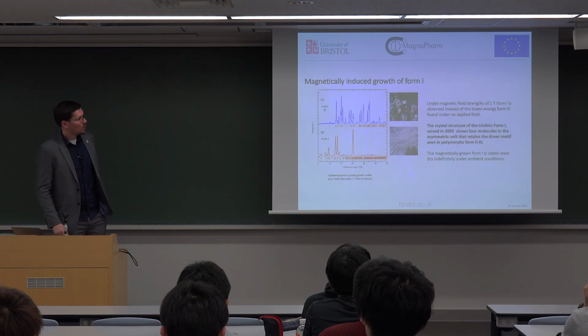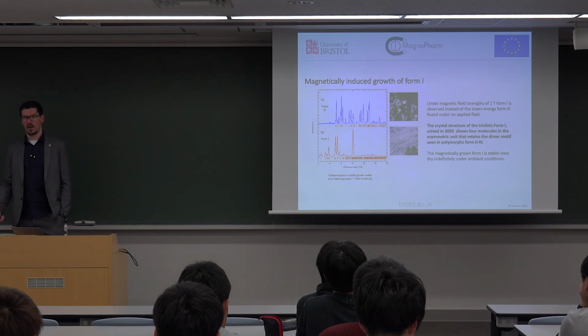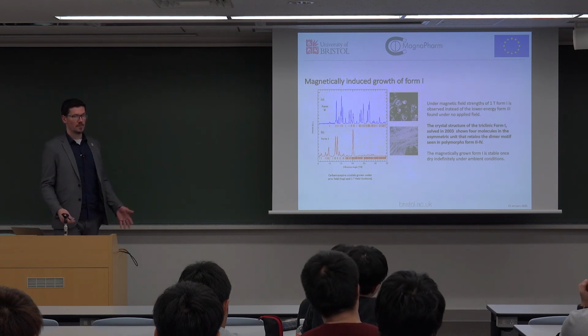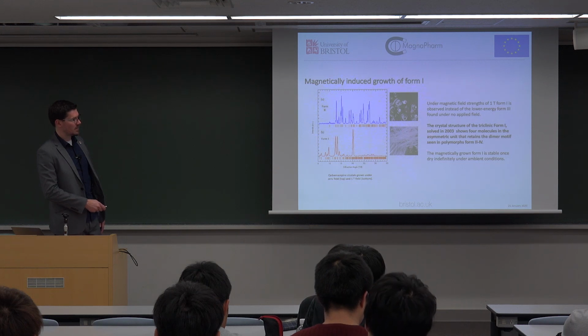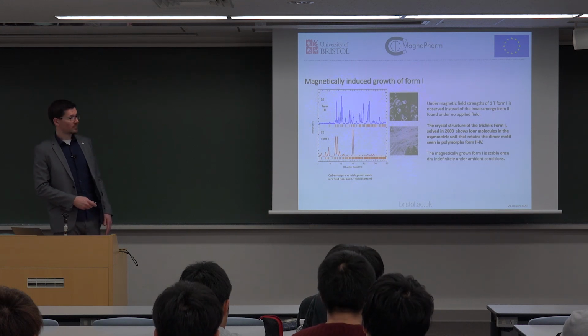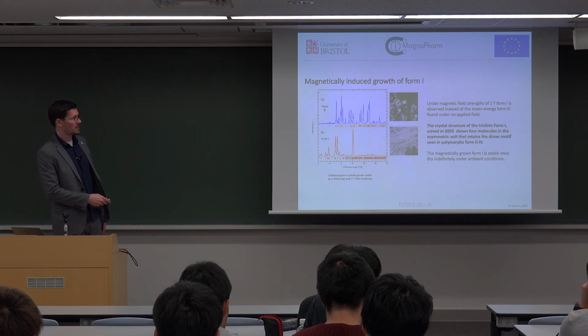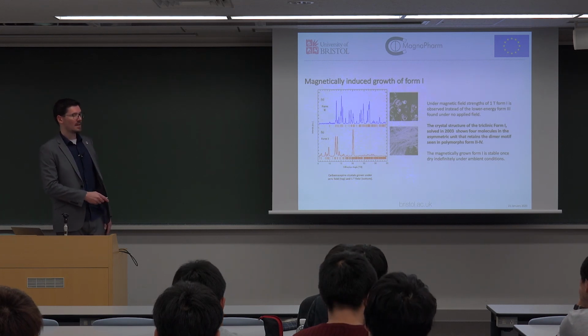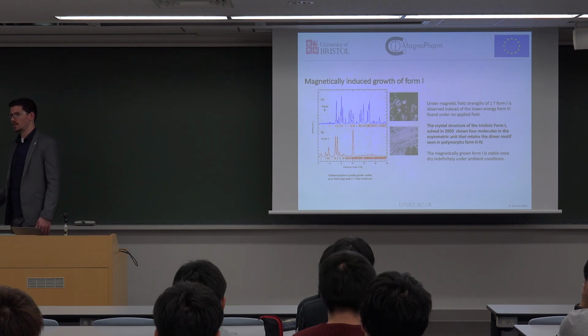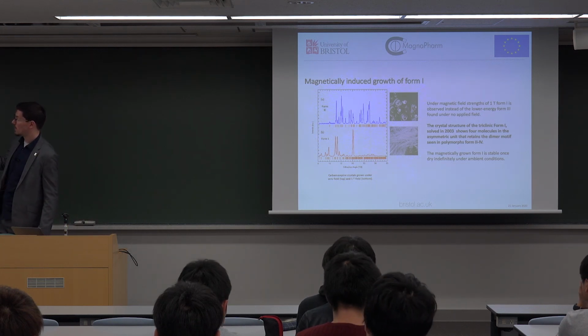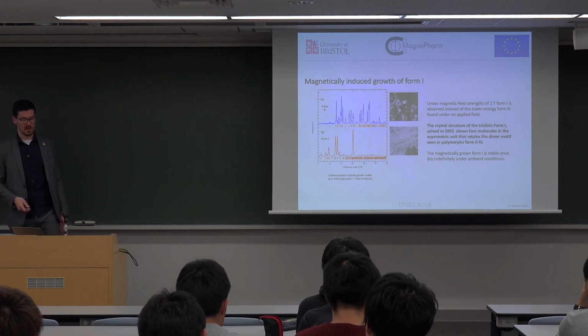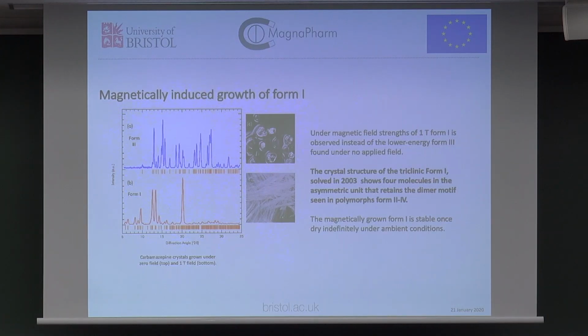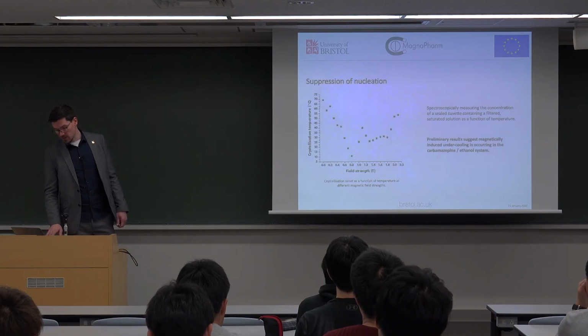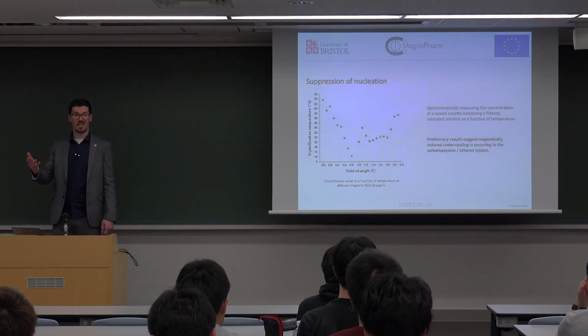Ooh. What we see is we do get polymorph selectivity. We go from form 3 to form 1. Form 1 is characterized by this fibrous form, long, high aspect ratio needles, and rhombohedral block-like crystals are characteristic of form 3. So we get form 3 out of the magnet, form 1 in the magnet. So great, it looks like we've got another system in which we have polymorph selectivity. Do we have the undercooling? Initial results would suggest we do.